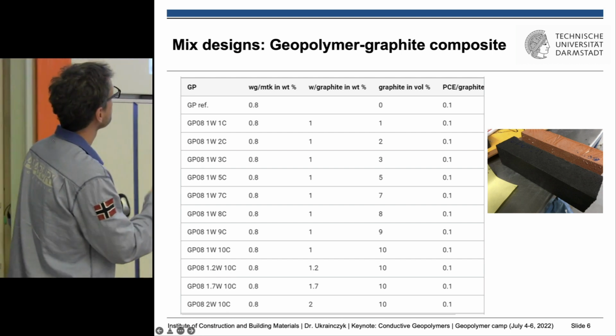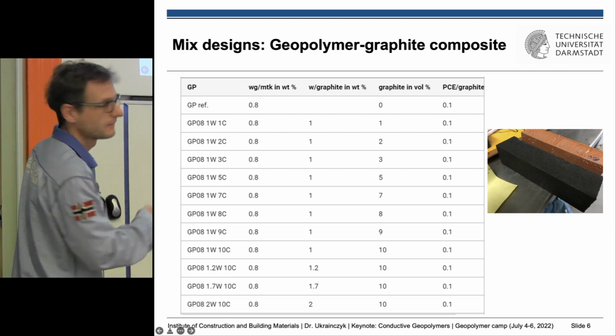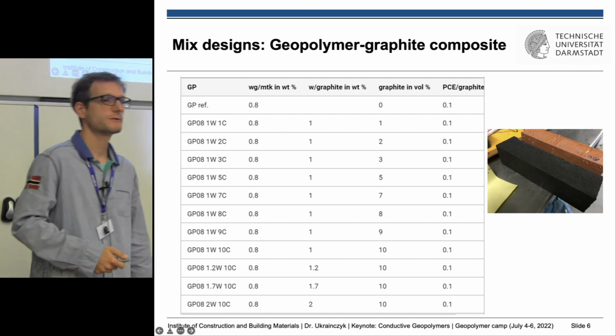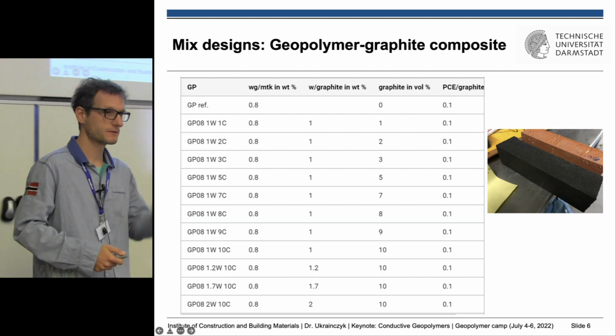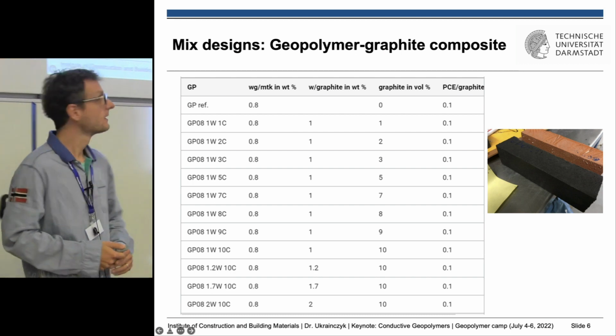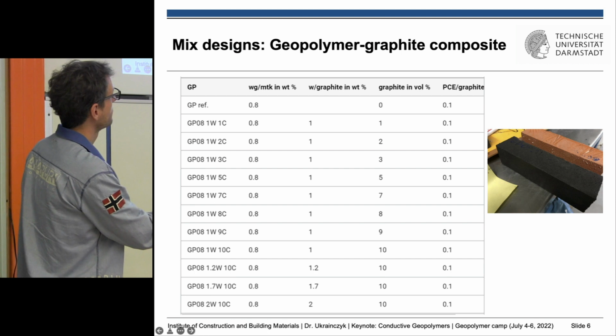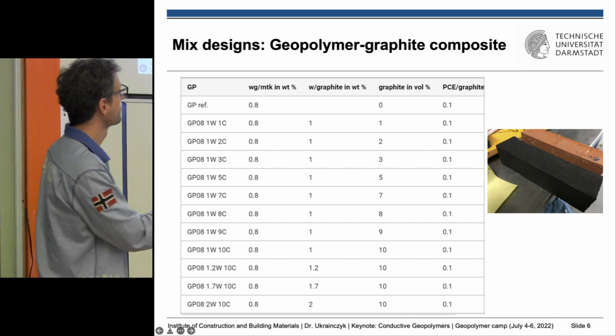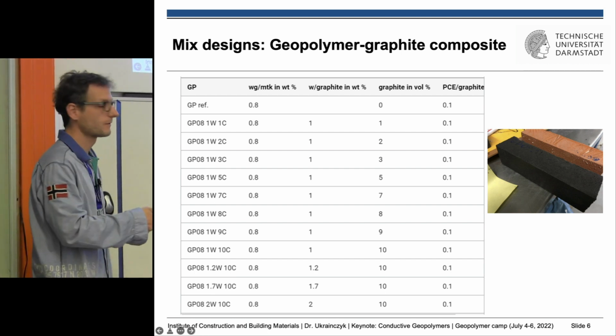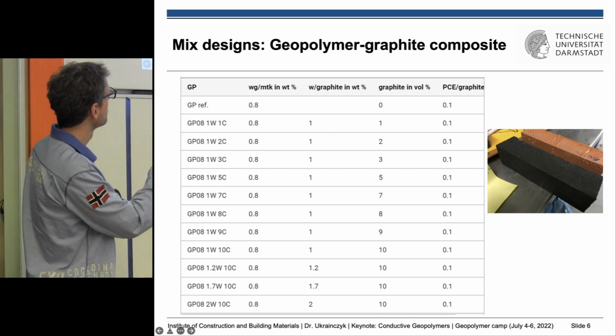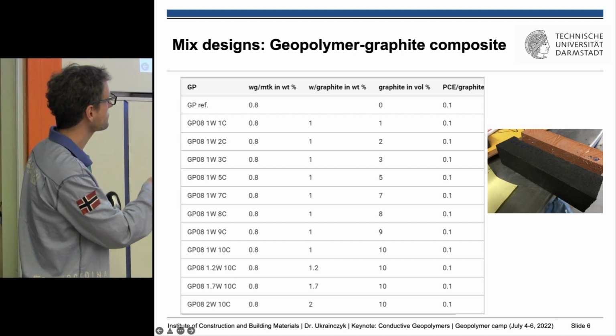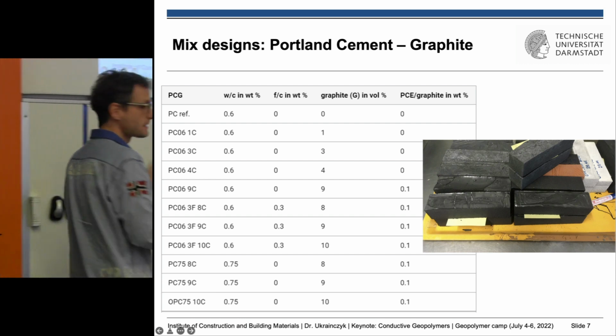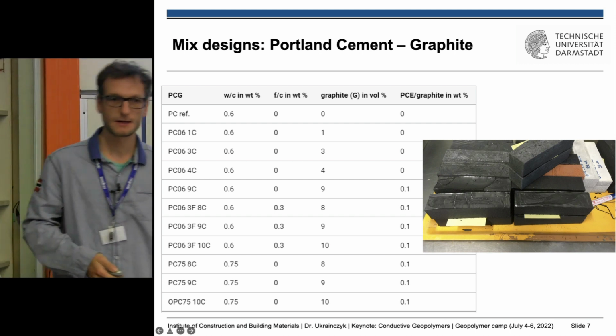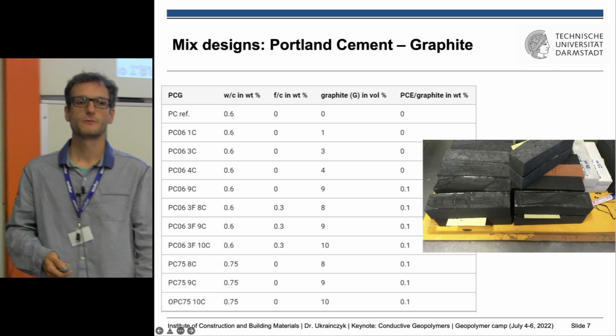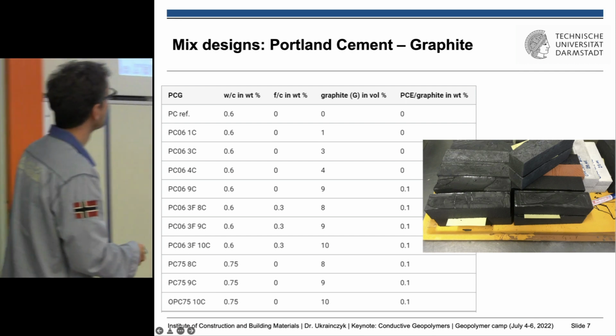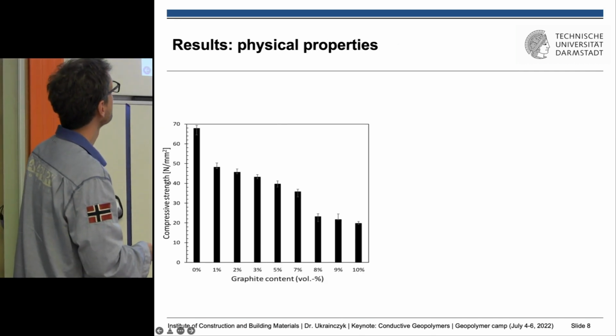But we also added water, and the water was added to actually increase the porosity, because now we want to play with the porosity. And then we fixed the 10% volume of graphite, but we added water. This is for Portland cement. We did a reference study, but they really didn't perform well. So I will not describe them here.